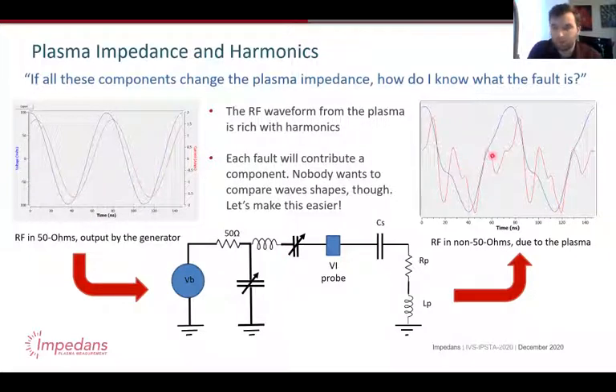And then when you take a real measurement of what these waves look like from the plasma's perspective, they're entirely different. You can see over here the voltage waveform is distorted a little. The current waveform is distorted a lot. There's a lot of what are called harmonic components because the plasma is a nonlinear load. So what you need to do for the future nodes is to measure this impedance, because if you want your process to be the same every single time, you want that impedance to be the same every time. And wear and tear on the chamber or even different wafers will change these waveforms that you see. So you can use the plasma itself almost like its own diagnostic.